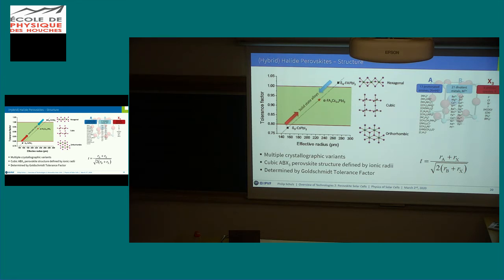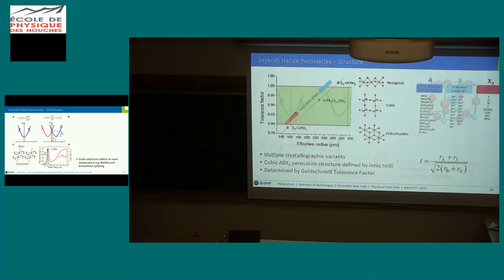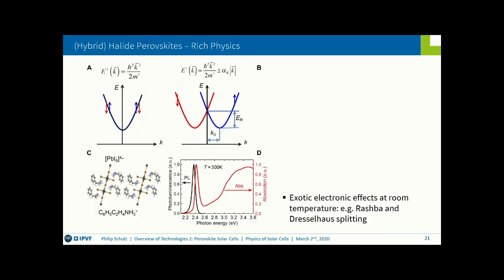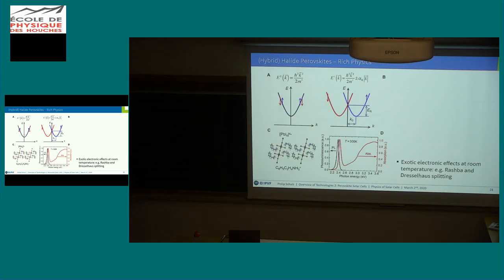And there is a stable window within which you form the cubic phase that is photoactive or absorbing at the wavelength that is interesting for us solar cell researchers, whereas deviations from this lead you into the hexagonal or orthorhombic phase, which are mostly transparent. And of course now, using all these different amines and metals and halide species, you can find combinations in which you are in the safe range. Now I want to skip these slides actually, so they are in your